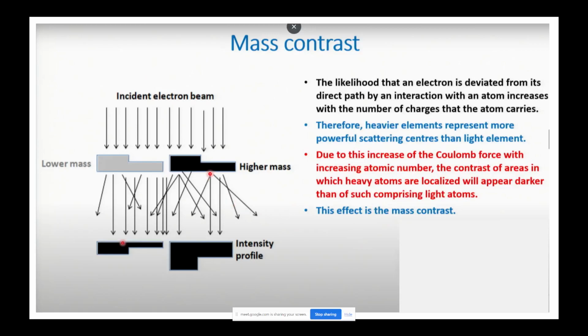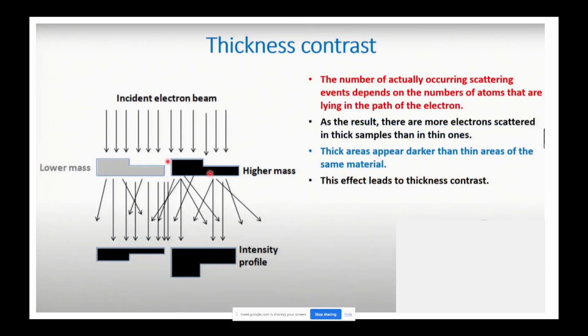So here, if you have two samples, one of lower mass and one of higher mass, in the lower mass you won't get much scattering, but in the higher mass you will get many scatterings. That's why the intensity profile will be different, and you will get a different contrast from the lower mass and the higher mass specimen. It is mainly because of your atomic arrangement, or the heavier or lighter atoms. Is it very simple? Now the thickness effect is also somewhat similar. Here also, the number of scatterings that actually occur depends on the number of atoms lying in the path of the electron.